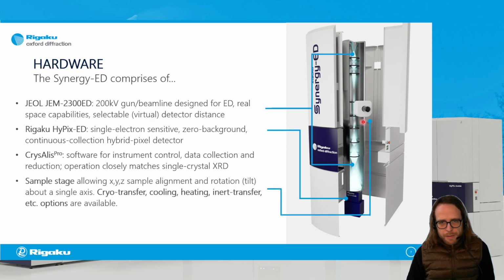Finally, we have a sample stage, which you see here. So the sample gets inserted into vacuum from here. And here, because we have designed this together with JEOL, who have a lot of experience with the vacuum stages, we have already a wide portfolio available with third-party suppliers for sample attachments that can handle cryo transfer, cooling inside the vacuum, heating inside the vacuum to above 1,000 degrees centigrade if necessary, inert transfer, even in situ systems where you encapsulate crystals between electron transparent membranes to insert some gas atmospheres, etc. There's really a lot available, and they are becoming more and more quickly.